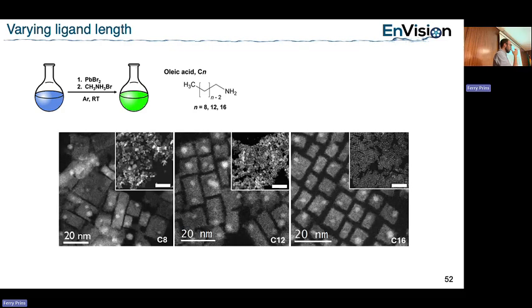The funny thing is that already just doing that, you see big changes. These are the TEM images - C8 is all over the place, and as you go to C16, the particles get better, more monodisperse. These bright spots you see in the TEM are artifacts because you're blasting the thing with electrons, so don't worry about that. But basically you're making the particles smaller and more monodisperse just by changing the ligand length - this is the binding of the ligand. You get better results at first sight.